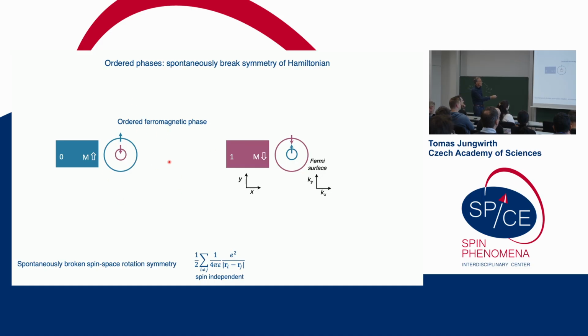Now, when you look into the momentum space, here you also see that the spin rotation symmetry is broken, because in this state we have the spin up being the majority band here, while in this other state the spin down is the majority band here. So the system is not anymore invariant under the continuous spin rotation. Now, all that's happening here, the spontaneous symmetry breaking associated with ferromagnetism, is happening in the spin space. So now the question is, how in the world can we detect this electronically? How can we distinguish those two states, which are different in terms of their spin rotation? How can we distinguish this by doing an electrical experiment? Because an electrical experiment is in the orbital space. But when you look at the two Fermi surfaces in the orbital space, they look exactly the same.